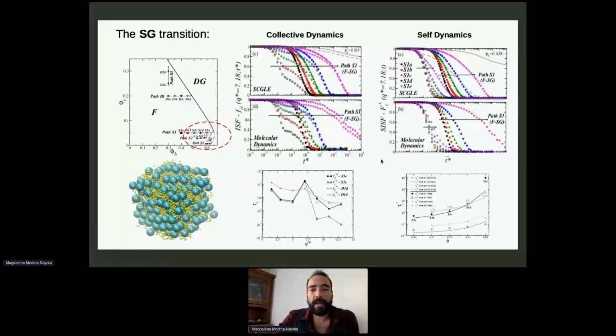For instance, if one looks at the correlation functions of the small particles, which are these empty symbols, and the big particles in both simulations and theory, one finds that approaching this single glass state, the self-dynamics becomes decoupled. This is observed in these dark black symbols and empty and filled symbols, which are the results of simulations, and the theory describes more or less the evolution of those relaxation times. But one can also explore different length scales and observe that the evolution of the collective relaxation times along this transition follows oscillations which are mediated by the structure factor, which is, as I will show immediately, different as observed by approaching this other transition.